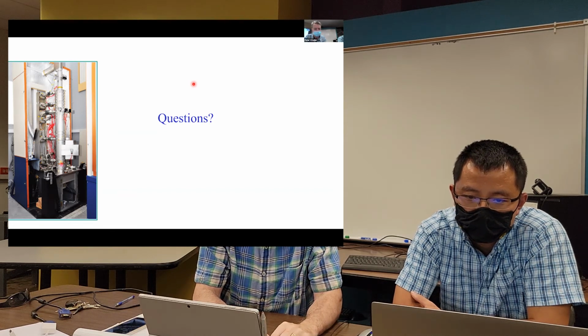Someone has a question here about EELS in the ARM. We often had issues with thickness, which the ARM requires to be less than 100 nanometers. I believe that the limitation still remains true for the Nion. My primary interest is iron oxidation state. Yeah, thickness is always an issue, depending on how the sample is prepared. Your sample typically needs to be 50 to 100 nanometers in thickness. But it's also very dependent on the form of your sample.